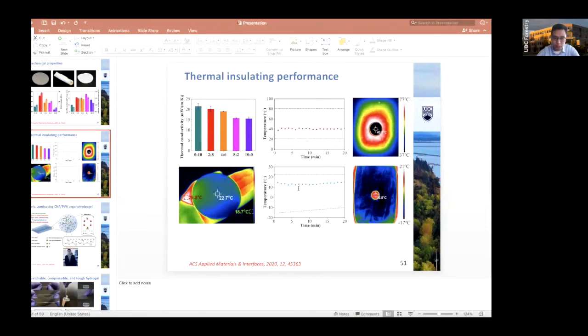Okay, one question. Have you tried other solvents in addition to sodium hydroxide urea during the DIW? This one has not been done. We do work in the lab with some other cellulose solvents, but not for 3D printing. There is some literature where other people have used other solvents, but for this work we don't want to completely dissolve the cellulose. Therefore, we chose sodium hydroxide urea because by controlling the time and the conditions, we can partially dissolve the cellulose.